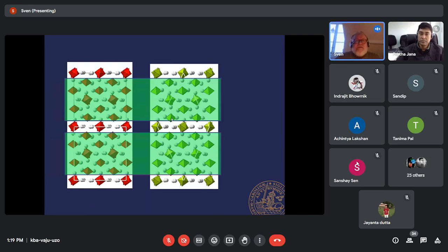If you analyze it a little bit closer, you will see that it actually consists of 2 types of blocks, which are displaced with respect to each other along the line of sight in this image, so that you can look at this as a stacking of slabs, and the left stacking is AB, and the right stacking is A prime B, because the A prime block has been shifted along the line of sight.